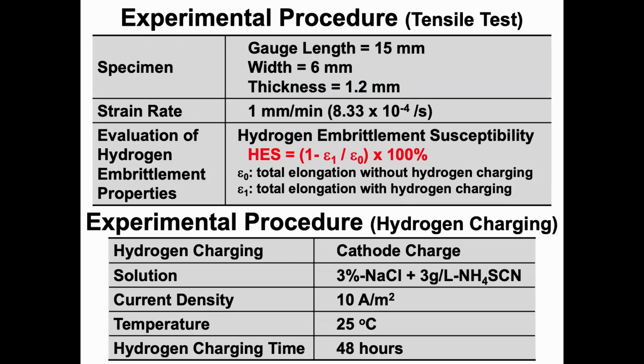Tensile tests are conducted using a tensile specimen with dimensions of 15 millimeter in gauge length, 6 millimeter in width, and 1.2 millimeter in thickness at a strain rate of 8.33 times 10 to the minus 4th power per second. Hydrogen embrittlement properties are evaluated by the hydrogen embrittlement susceptibility, HES, using this equation, in which epsilon 0 and epsilon 1 denote total elongation without and with hydrogen.